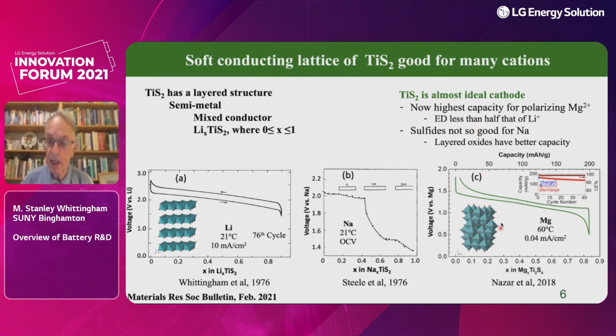In this case, this is a spinel phase. The layered phase is very similar. And you can see this cycles very well. She has shown 40 cycles on this. But the downside of magnesium is it needs to be at 60 degrees centigrade, and the current density is much less. So the use of magnesium, sodium, and potassium helps us understand ionic transport in these materials, but we shouldn't really think that magnesium is going to be a viable rechargeable battery. Its voltage is just too low. You can see it's almost a volt below lithium.